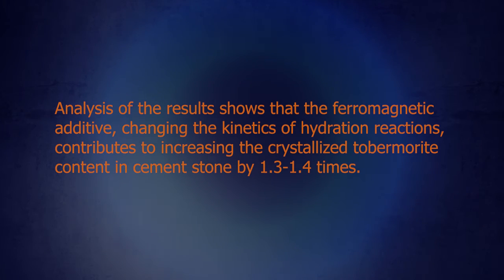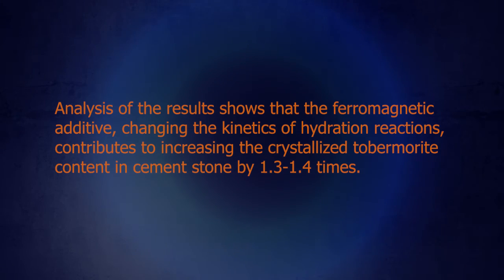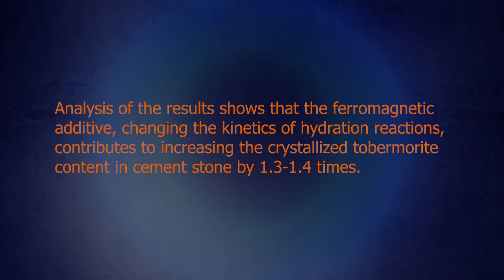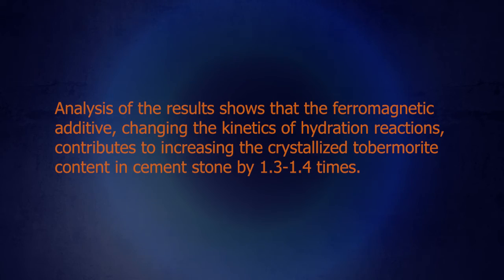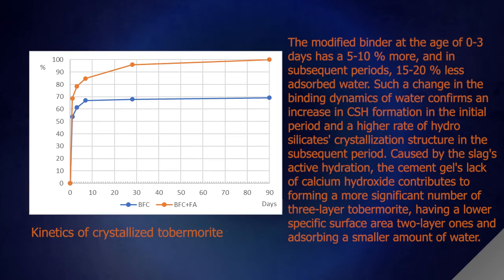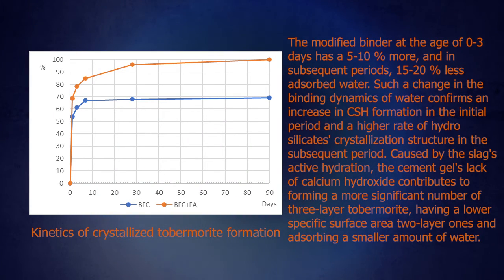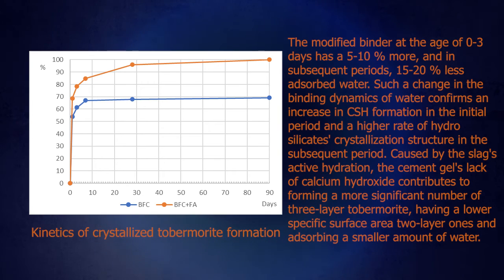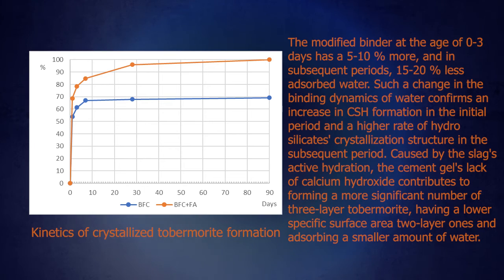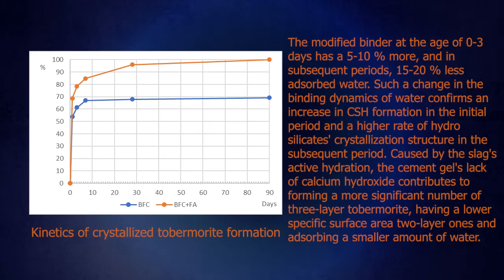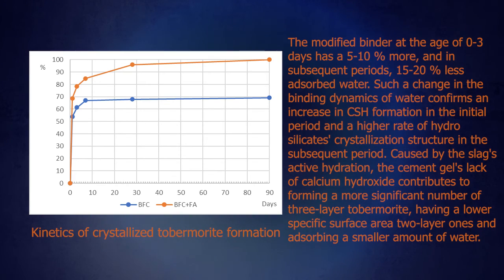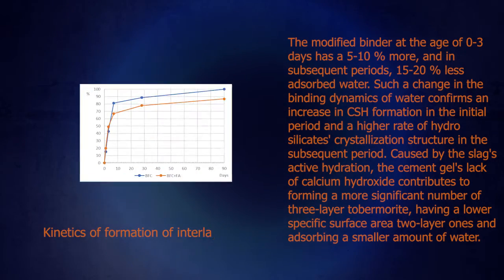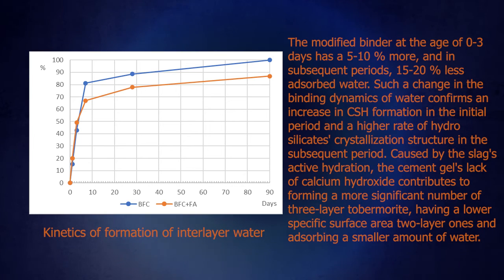Analysis of the results shows that the ferromagnetic additive, changing the kinetics of the hydration reaction, contributes to increasing the crystallized tobermorite content in cement stone by 1.3-1.4 times. The modified binder at the age of 0 to 3 days has 5-10% more, and in subsequent periods 15-20% less absorbed water. Such a change in the binding dynamics of water confirms the increase in CSH formation in the initial period and the higher rate of silicate crystallization structure in the subsequent period.